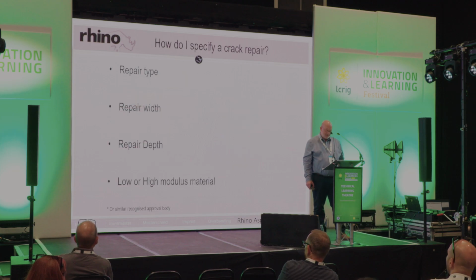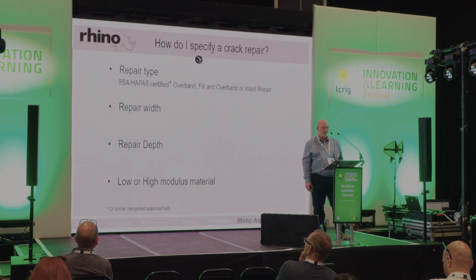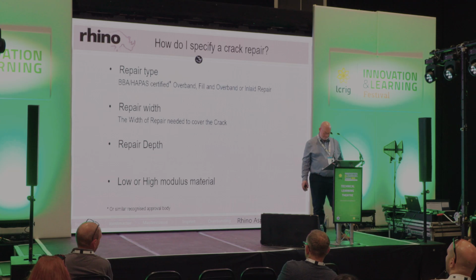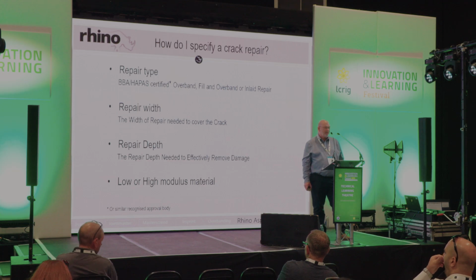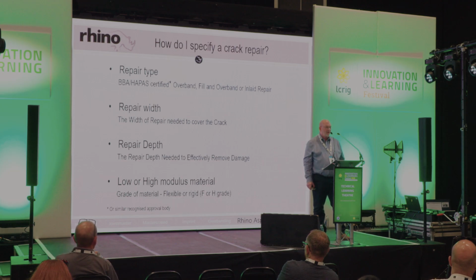So how do I specify a crack repair? Well, initially it needs to be a BBA HAPAS approved system or a comparable certified system. The repair width. Now, this is the width of repair that's needed to treat the crack, not the crack width. We often get asked to repair a certain crack width, but that's not really much use to us. We need to know how wide the repair needs to be. Also, the repair depth. How deep do we need to repair that crack? It may be 20 or 40 millimeters deep. Then lastly, what type of material? Will it be a high or low modulus material, flexible or a high modulus repair?